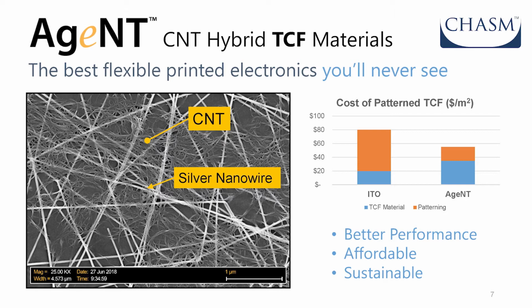Here you see an example of a carbon nanotube hybrid, which has a silver nanowire film, the shiny rigid rods here, and then this noodle-like structure is the carbon nanotubes that have been printed on top of the silver nanowire film. We have a very simple process for fabricating circuits. It's called print, etch, done.